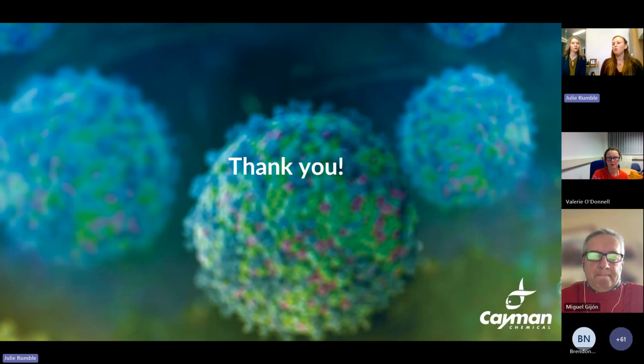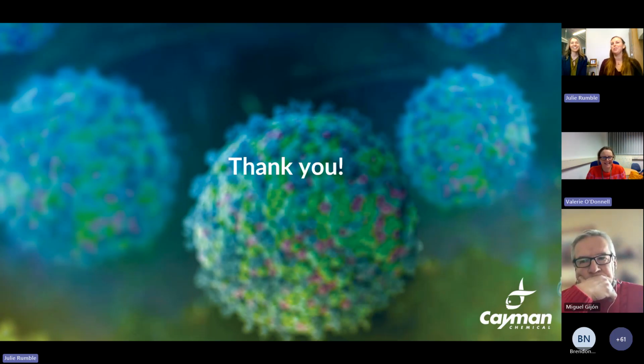Yeah, completely. So I think the most attractive way of approaching that right now is using click chemistry. And so you can include one of the click partners as a DSPE PEG with an activated moiety on the end of the PEG, and formulate your LNPs in that way, and then add the appropriate click protein on the other end. We're actively working on that right now. We haven't solved the problem yet, but we're getting there.